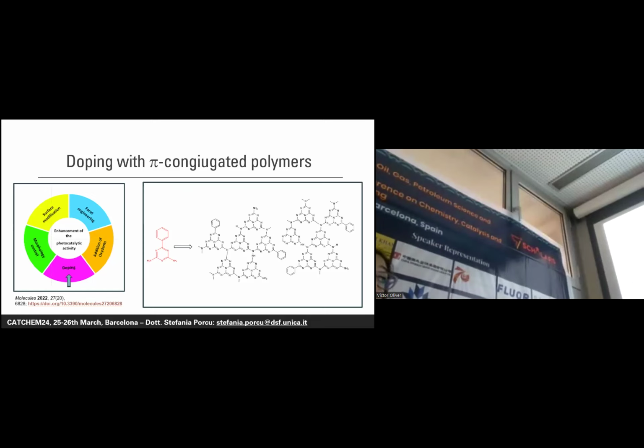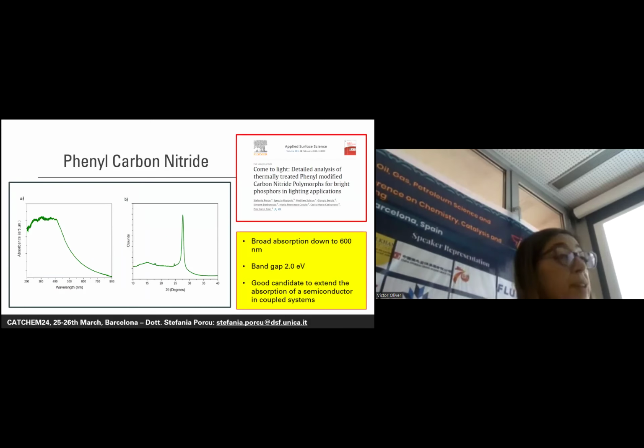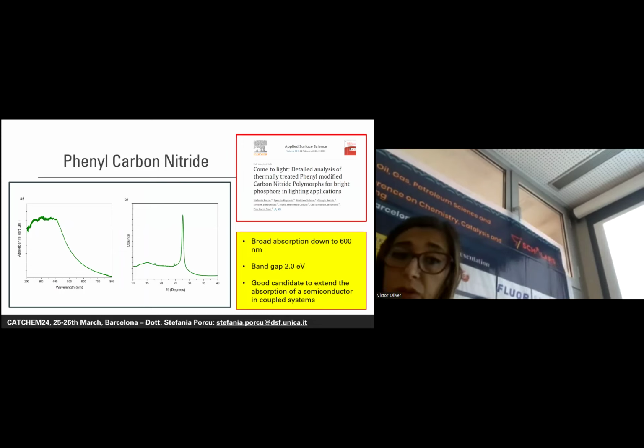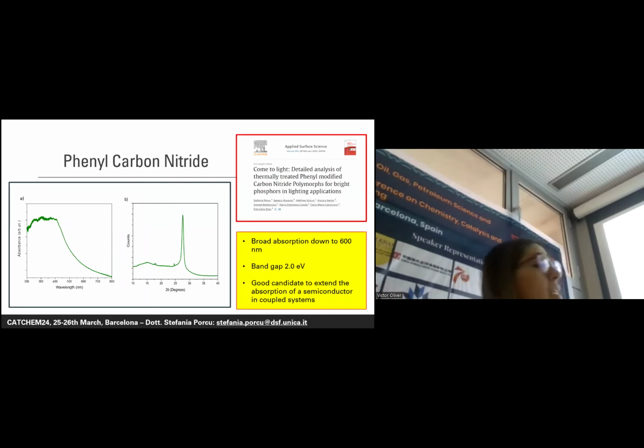This material has been obtained starting from a phenyl substituted triazine, the monomer highlighted in red in this slide. What we did was study the polymerization process of this material, changing one parameter at a time, such as the temperature and the environment of the polymerization. What we found was a very promising polymer, which I'm going to talk about now, that we obtained by polymerizing the phenyltriazine at 400 degrees under nitrogen for only 2 hours. It was a solid state polymerization process.